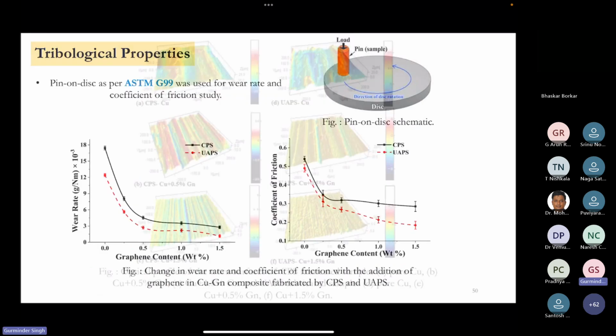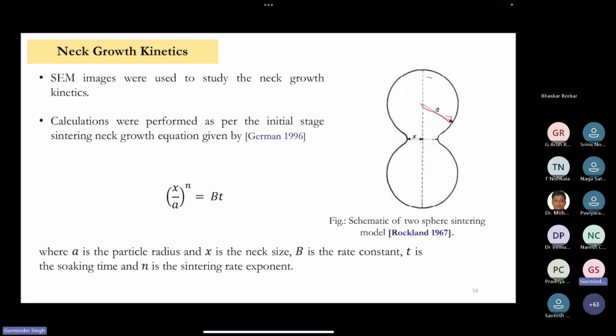So experiments are fine, but it is always good to verify the data using some mathematical relations. So we have chosen the mathematical relation of a two spherical model by Rockland, where we have two particles having the same shape and the same diameter, and the neck will grow with respect to the rate x over a raised to n. Here a is the radius of the particle, and x is the cross section of the neck, which will grow with respect to temperature.